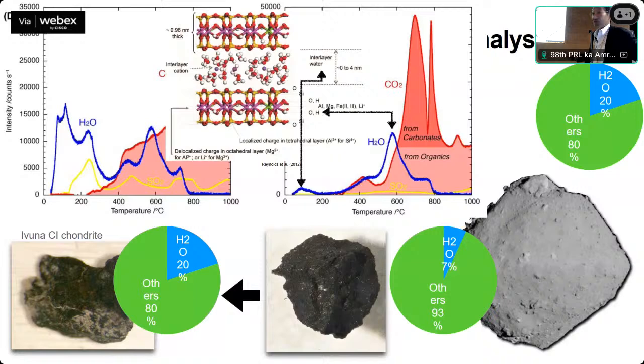So let's compare with CI chondrite. You see, this intensity is similar to Ryugu. But this intensity at 100 degrees is much larger in CI than in Ryugu samples. This is because CI has interlayer water, but Ryugu does not have interlayer water. Why? Because interlayer water is easy to evaporate. So in vacuum conditions such as space, all of the interlayer water should evaporate. Therefore, the water content in Ryugu becomes 7%.